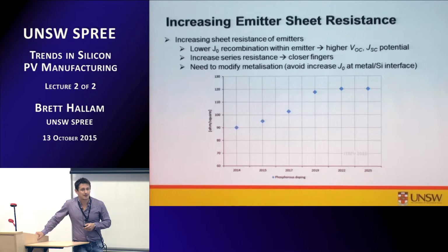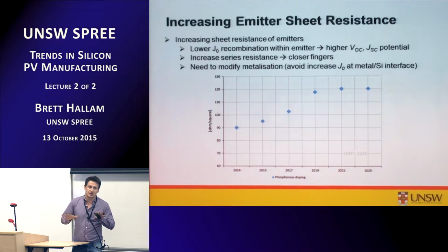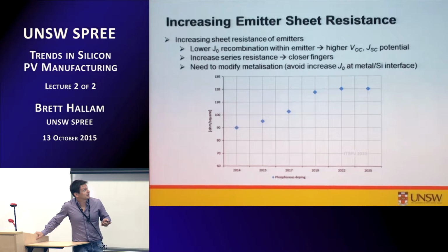But getting back to what is actually happening with the sheet resistance, it's always going up. It's been going up for the last 10 years pretty clearly, and a lot of this is we want to reduce the J0 of the emitters. So the emitters have different recombination. Bram highlighted the Auger recombination within the emitter. If you have a really heavily doped emitter, you have Auger recombination within that emitter due to all of these extra dopants. But then you've also got the surface effects like Bram mentioned, etc. Generally a higher doping is better to reduce the minority carrier concentration, but it all can affect this J0, the emitter's dark saturation current density. And generally we want to go to a low J0 recombination so we can get higher VOC and JSC potential. So that's what we're shifting towards, but that creates a lot of challenges for the metallisation and how we make the solar cell.